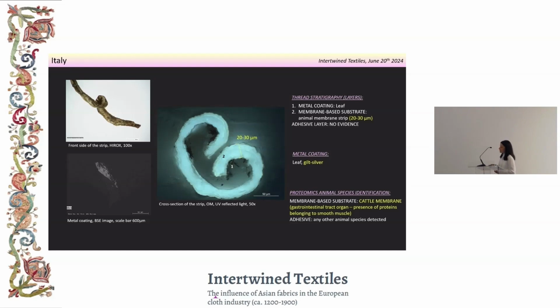And we didn't find evidence of any adhesive in this case, neither in looking at the sample in cross-section nor by proteomics analysis. However, an adhesive can also be present, but if it was of the same animal species as the membrane, we are not able to distinguish it. So we need to further investigate and understand if they used any kind of adhesive to join the metal to the strip. And in this case, the coating is less precious, so we have gilt silver coatings.